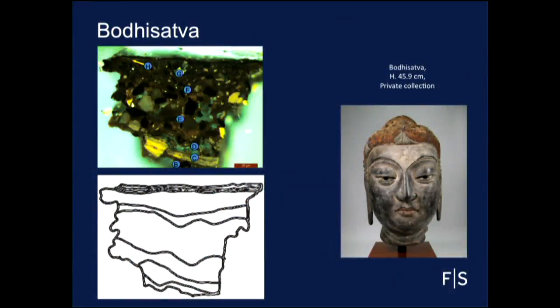The Bodhisattva also has 5 layers above the textile, followed by a layer of paint and soil, very thin layers at the top. In the Bodhisattva, bone, as well as possibly heat-bodied Asian oil, unidentified tannins, starch, and possibly blood were found using GCMS.